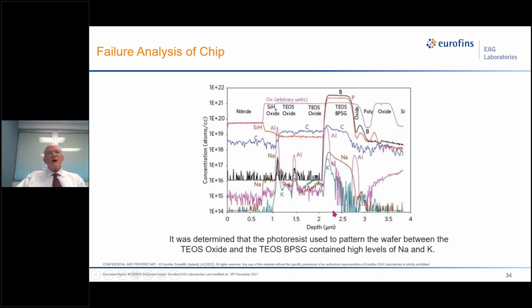And there was one question about, can you analyze lithium? It's very light. It has miserable sensitivity by any electron spectroscopy technique. But by SIMS, it's quite sensitive. It's an alkali ion, and I just didn't measure it here, but I certainly could have included lithium in this analysis. And our standard actually is an ion implant standard in SiO2 of lithium, sodium, and potassium, all in the same sample. So failure analysis, this was a great success.